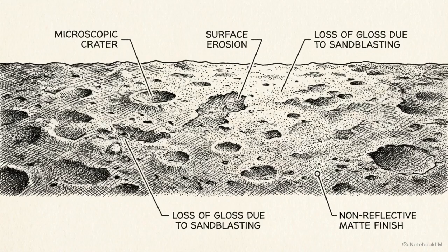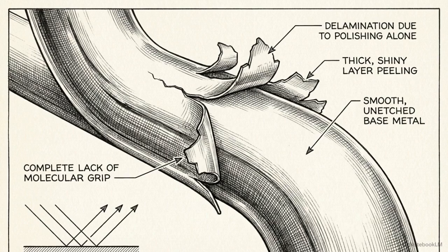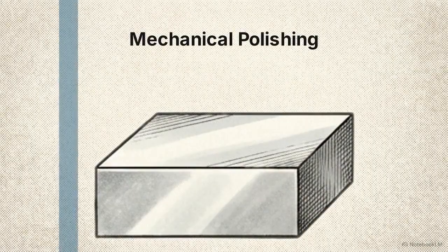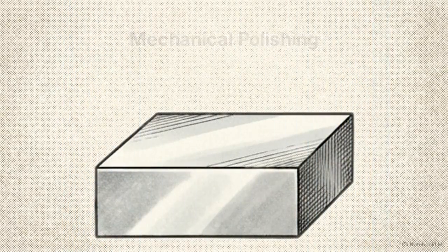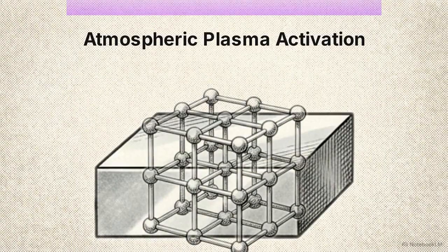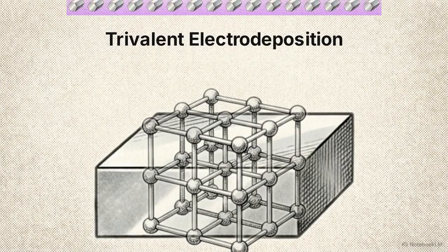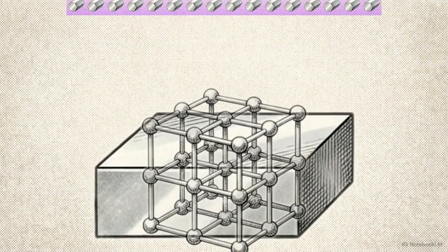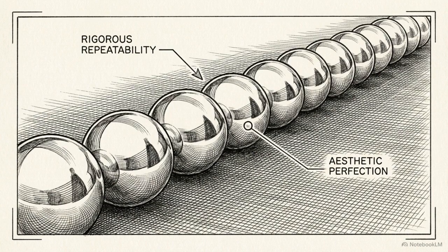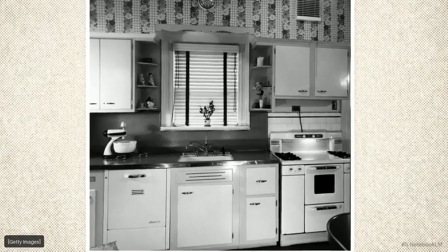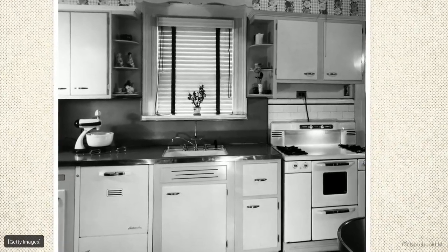Sandblasting raw metal yields high adhesion but destroys the possibility of gloss. Polishing the metal alone yields high gloss, but guarantees the coating will delaminate and peel. The successful sequence starts with mechanical polishing to create a flat baseline. Then, atmospheric plasma activation boosts the surface free energy, preparing the metal for molecular bonding. Finally, precisely calibrated trivalent electrodeposition controls the crystalline growth to build the dense, reflective coating. The result is a rigorous, repeatable process that produces highly durable, aesthetically perfect finishes on everything from aerospace components to the oven handles and sink fixtures of a vintage kitchen.